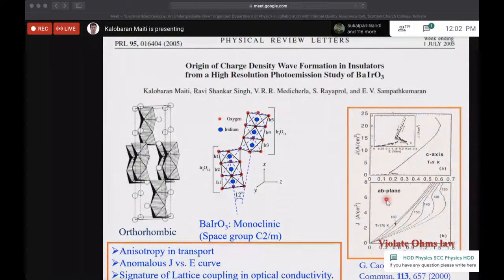But if you cool it down, you can see that, for example, at 120 Kelvin, it goes somewhat linear, but then here it shows non-linear behavior. You see, as it goes down, a negative slope, which is very unusual, which you don't really expect in any material. Okay? So why is it happening? It's an insulator. Normally you don't expect this kind of behavior.